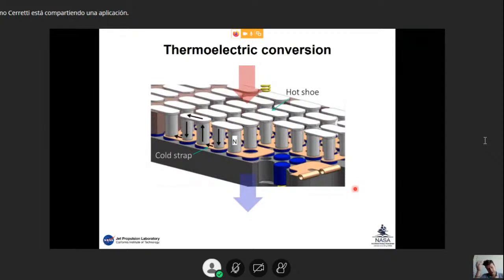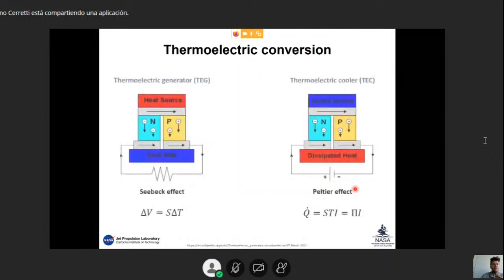So this is a schematic view of what a thermoelectric module looks like. It's formed by several P and N junctions that are electrically connected in series and thermally in parallel. Thermoelectricity works mainly through two effects. On one side, we have the Seebeck effect, which is used in thermoelectric generation. In this case, when we apply a temperature difference at the p-n junction, that induces a migration of the charge carriers, which are electrons on the n side and holes on the p side, from the hot side to the cold side, and that generates a voltage. The voltage is then proportional to the Seebeck coefficient of the materials and the delta T, the difference in temperature between the hot and the cold side.